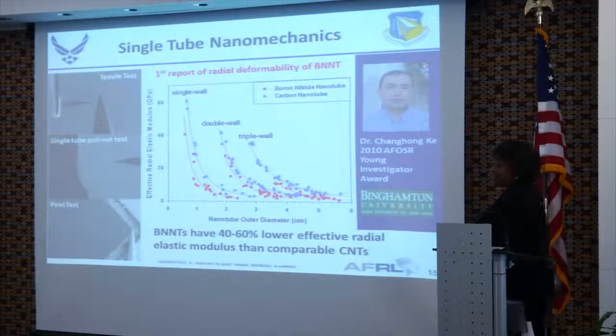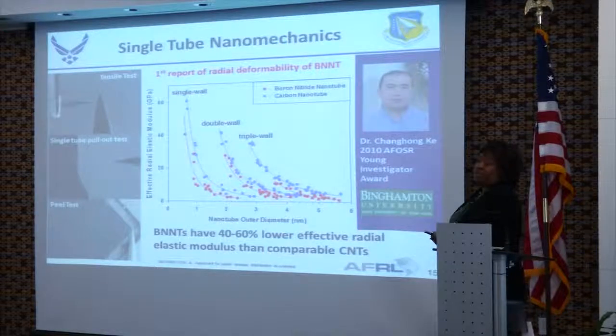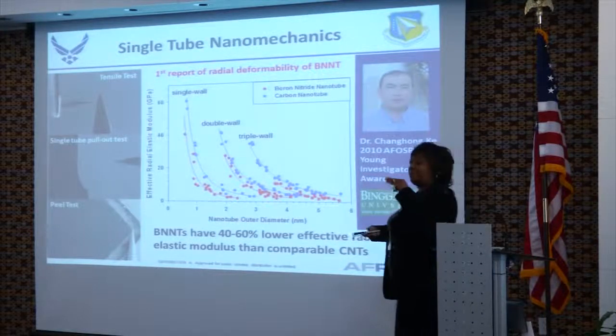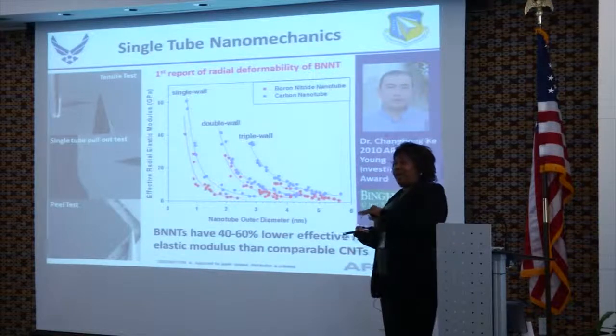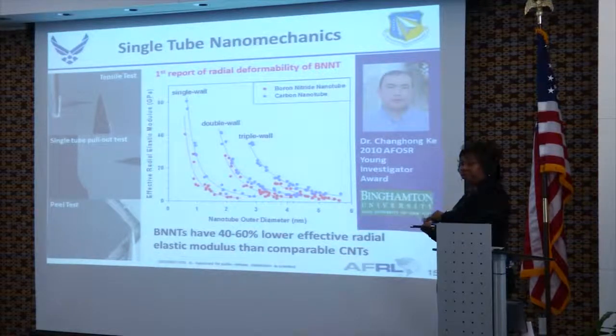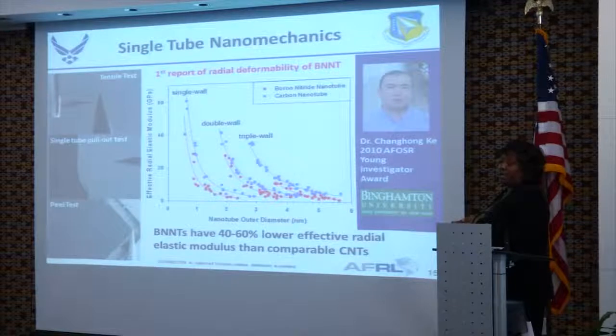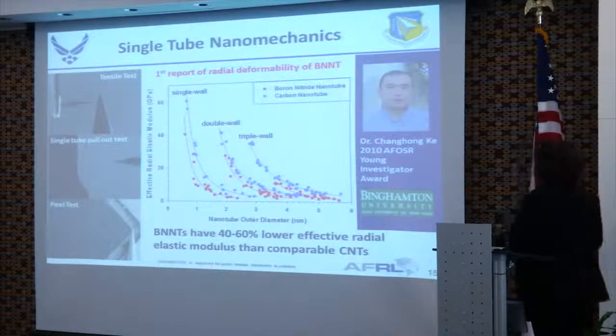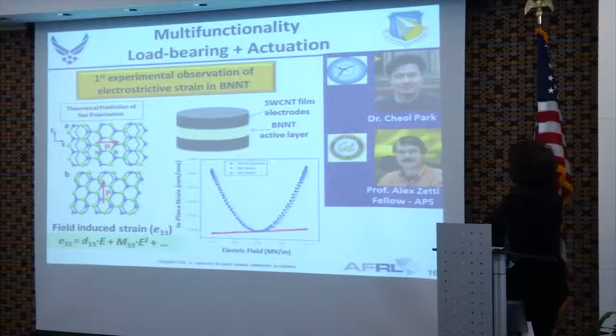And they have very interesting implications because I mentioned band gap engineering for boron nitride. The band gap decreases as you deform these, and so you can more readily deform these than something like a carbon nanotube. That also has implications for mechanical reinforcement because, as I mentioned, you want to get that deformation to get good coupling between the tubes when you're looking at mechanically consolidating these. So these are very interesting results.